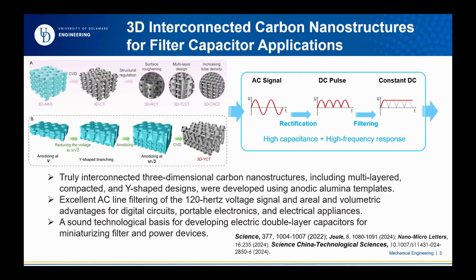So we end up with a three-dimensional structure, interconnected horizontally and vertically. That can provide very high frequency response, because for AC to DC conversion you need a very high frequency response, typically cut at 120 hertz. So we look at the response, what capacitance you have. Since this interconnected structure is based on carbon, a very good conductor, we can achieve high capacitance and, at the same time, very high frequency response at 120 hertz. We did a series of experiments.